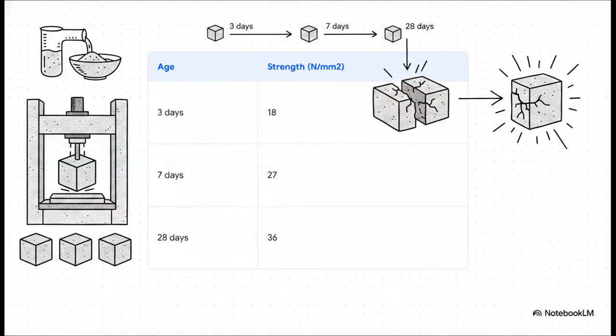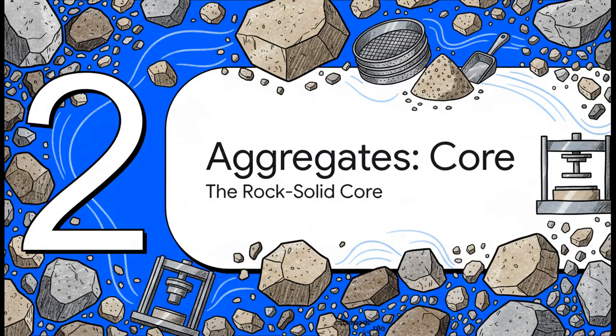Finally, the cement goes through a brutal crushing test. Technicians mix the cement with sand in a 1:3 ratio, add a very precise splash of water, and mold these perfect 70.7 millimeter cubes. Then, they take those cubes and literally crush them in a powerful hydraulic press. And the standards are unforgiving. Ordinary Portland cement has to survive 18 newtons per square millimeter of pressure at 3 days, 27 at 7 days, and a whopping 36 at 28 days. It's a rigorous way to prove, without a doubt, that the material is reliably gaining the strength it needs over time. Moving right along to Section 2, aggregates, the rock-solid core.